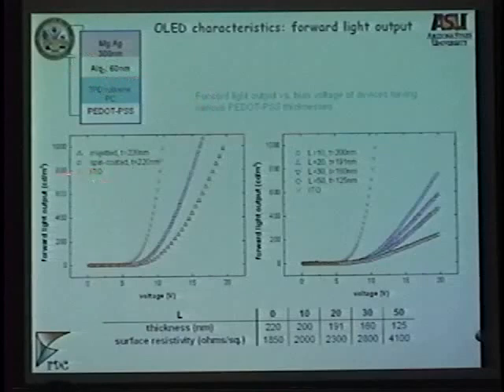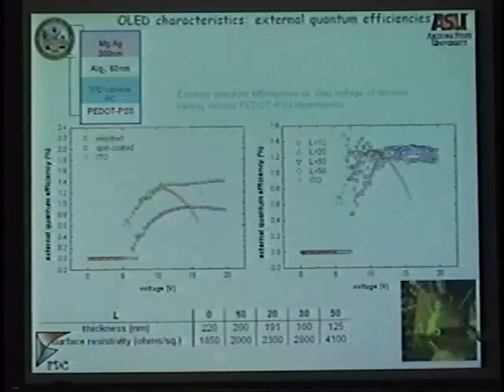So here you see ITO devices, then spin-coated devices without any ITO, and inkjet devices without any ITO. And as you might expect, ITO has a much lower sheet resistivity, therefore it can allow for a given voltage much higher currents than what you could see for PEDOT, either spin-coated or inkjet. Now, if you go down here, I'm going to skip this in the interest of time.